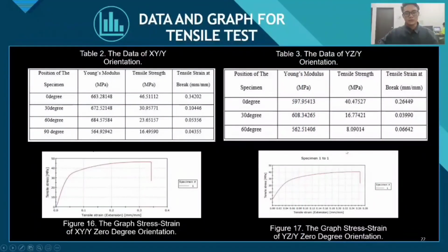So for the data and graph for the tensile test, table 2 shows that the XY/Y orientation, which is defined as the 60 degree position, has the highest Young's modulus value with 684.57584 compared to others. And for the YZY orientation, the 30 degree position of the specimen has the highest Young's modulus value, which is 608.346265 megapascal compared to others. The curve of the graph for XYZ is higher than the curve for YZY in the stress trend for the 0 degree orientation.